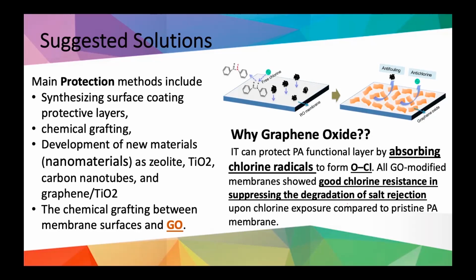Why graphene oxide? Why are we stressing on graphene oxide? My group and I have previous publications on graphene oxide, but now we are trying to have a new look at graphene. Why? Because graphene, as I said before, was only embedded in the aqueous solution or the aqueous layer, to be cross-linked by the organic layer forming the TFC membranes. So we are now trying another way of getting benefit from this graphene. Why graphene? Because graphene is very, very powerful in absorbing chlorine radicals.